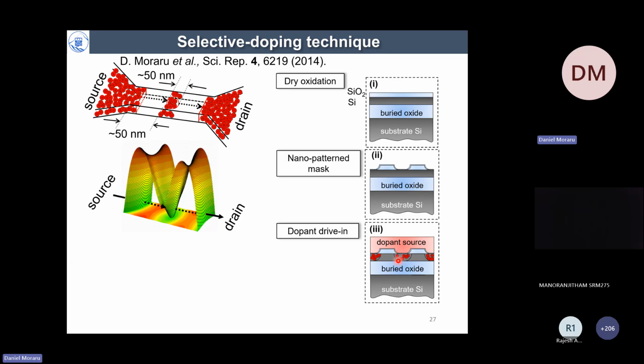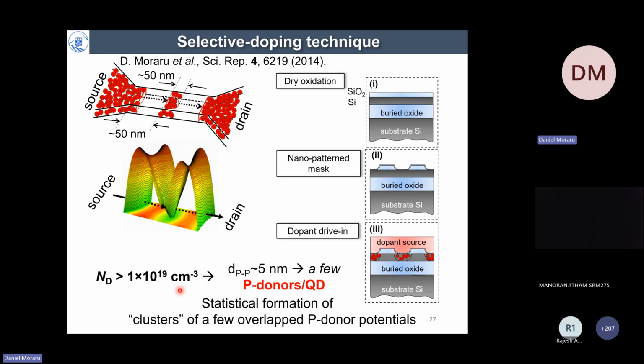Nevertheless, we should be aware that there is side diffusion, so it's not a perfect process. It still needs to be optimized in the future, but it allows us to build molecules of a few phosphorus donors. We raised the doping concentration macroscopically by one order of magnitude, to 10^19, and in those conditions, statistically, we can form clusters of just a few overlapped phosphorus donors in the middle of this channel, and we have a little bit more control over the location and the structure of a device.